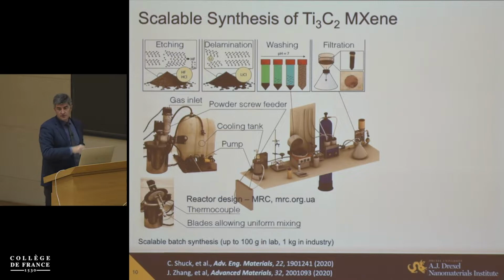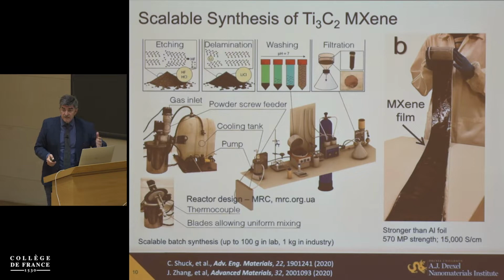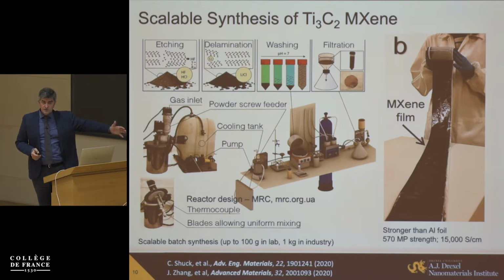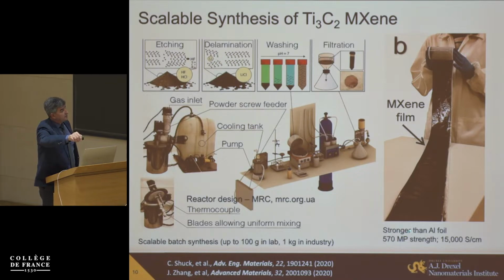per batch here. So if you take two-dimensional materials, you can cover a huge area with this. 1 kilogram reactors are already in industry here. And what is important, we can process it right away from the solution that we dispersed in water. And this is, you see, like a 1.5 meter long film. Actually, just 1 micron. This one is supported. If you make it 3 micron, it will be self-supported. You can basically handle it, cut it, make a paper, an MXene paper airplane out of it here.